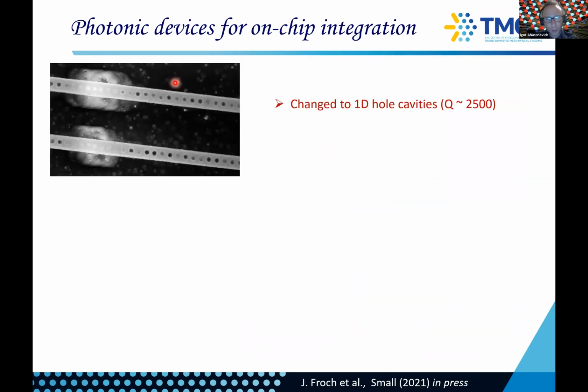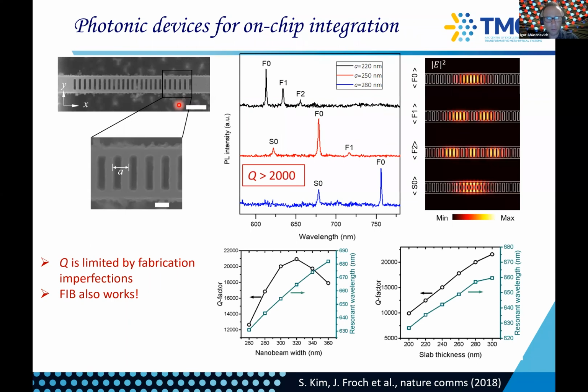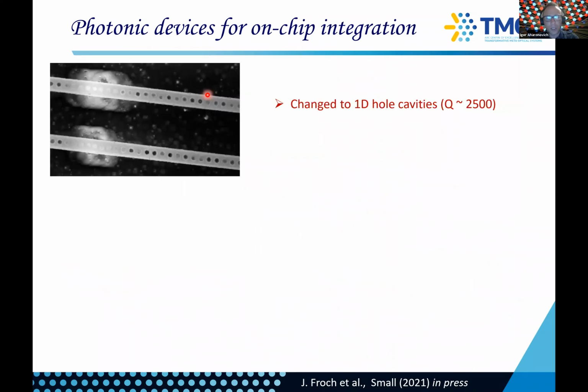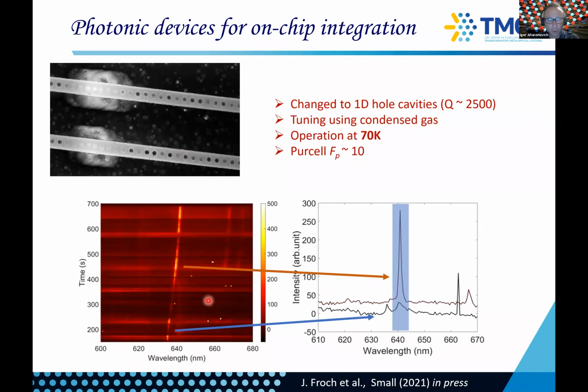You can then move to holes. The reason to move to holes is just better confinement in the middle, so you can create your emitters. And so you can move here to 1D, but with holes, photonic crystal cavities. And now for the first time, we could actually see some sort of tuning. You can see here, this is the cavity mode that we tune by just gas condensation, and this was the emitter here.